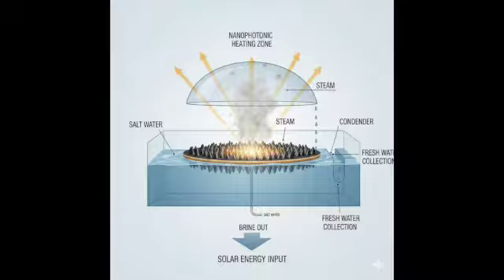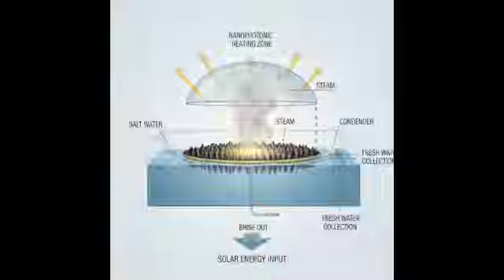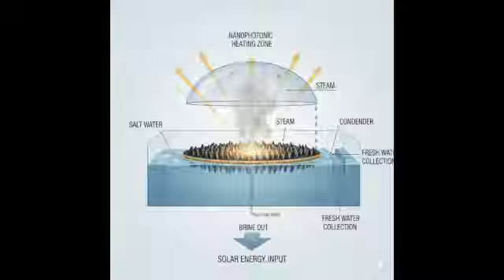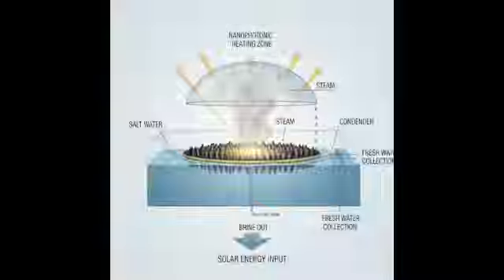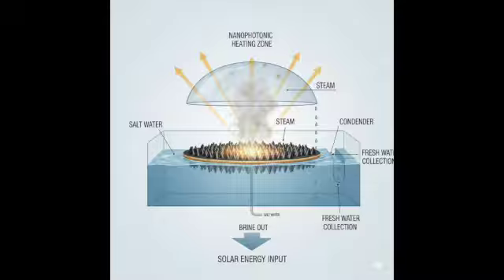Okay, moving on. What about metal oxides? Things like titanium dioxide, zinc oxide, ZnO, iron oxide. Metal oxides are attractive because they are generally considered stable, abundant, and low toxicity. They work as semiconductors. How do they generate heat? They absorb photons with energy greater than their band gap, creating electron-hole pairs. When these pairs recombine or relax, they release the excess energy as heat. They can also induce surface nanoroughness, which can help with anti-wetting properties.